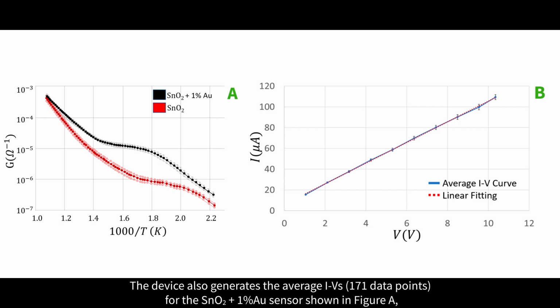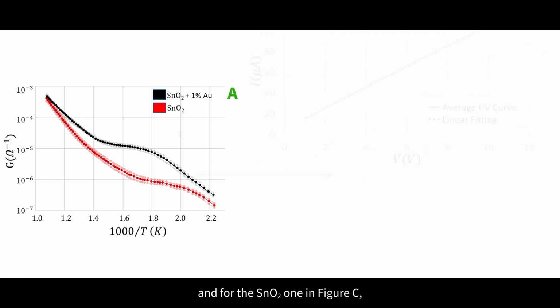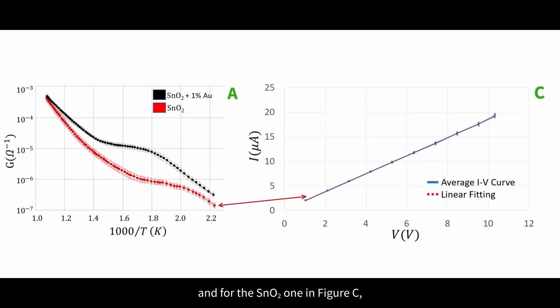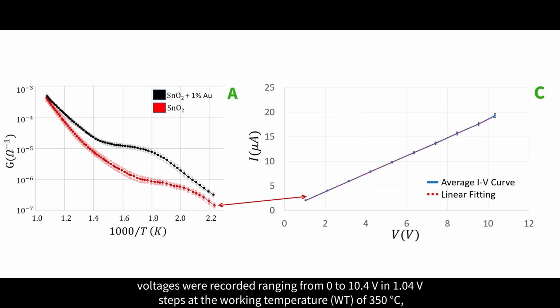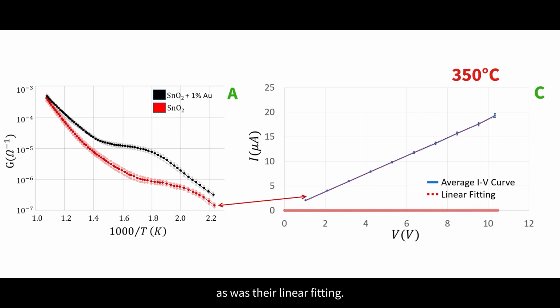The device also generates the average current to voltages for the tin oxide plus 1% gold sensor shown in Figure A, and for the tin oxide one in Figure C. Voltages were recorded ranging from 0 to 10.4 volts in 1.04 volt steps at the working temperature of 350 degrees Celsius, as was their linear fitting.